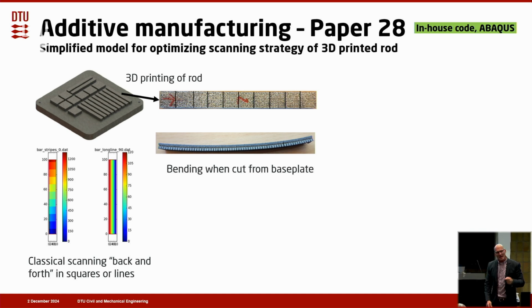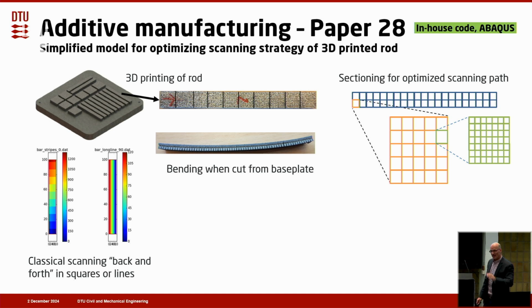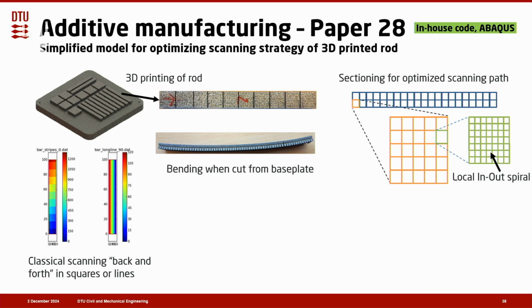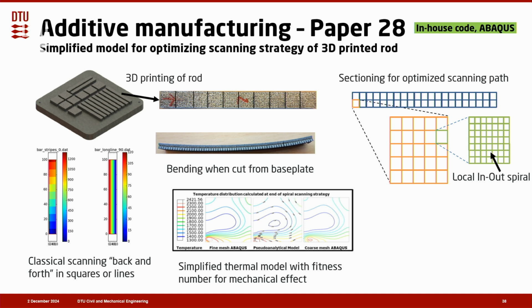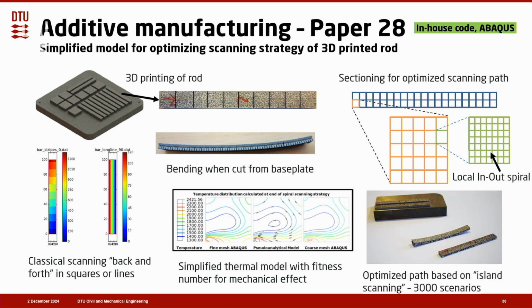So we thought, okay, how could we scan in another way so that it didn't bend? We sectioned this part in different levels, and in the green levels we used the so-called local in-out spiral scanning strategy with the laser. We made a simplified thermal model, and then we compared that for the local in-out spiral with an advanced model in Abaqus, and we saw quite good agreement. Not the same, but relatively good agreement. Then we could use that optimized solver to ask the computer, please tell us how to scan so it doesn't bend when it's cut off. The one below the bending one was the one with the optimized scanning path, and it was as flat as it was when it was not removed from the base plate.